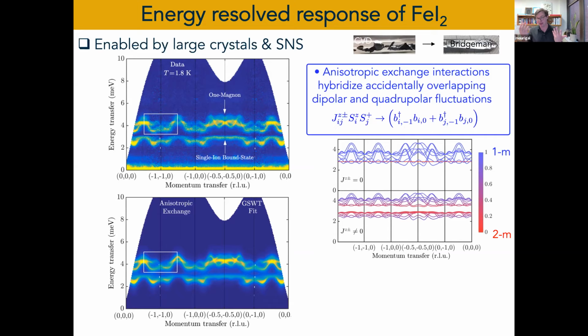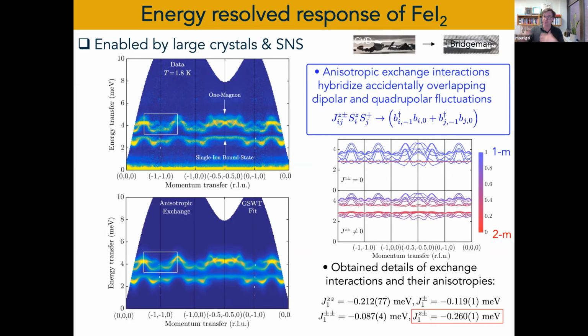And you can see here, this is a plot from Christian's group, where if we don't have this off-diagonal exchange interaction, you see our magnons, we have four branches because the unit cell has four sublattices. And you see this two magnon excitation here is the red line. It's just there. There's nothing. It's not visible. But when you couple it through the off-diagonal interaction, you see that everything starts to resemble the data. Okay.